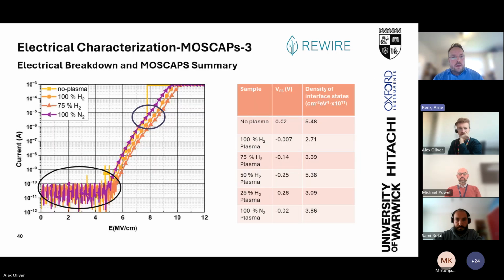Next slide, please, Alex. Then also another thing every device engineer will ask you about when they talk about gate oxide is, yes, but how about leakage currents? How about leakage in my device? We also tested this, and we got a breakdown, which you see here at around 10 megavolt per centimeter, which is where you would expect it, maybe even a little better than what you would see with the thermal oxide. Here as well, another key performance indicator, they outperform what's currently out there.